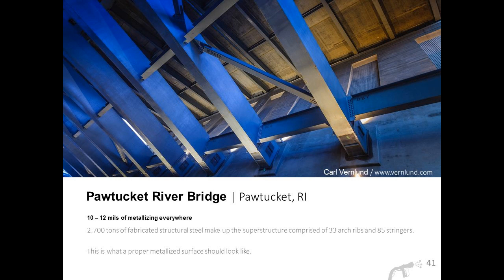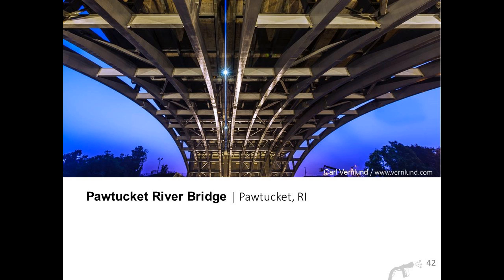So metallizing was used and was applied at a volume of about 10 to 12 mils and, like I said, seal coated and erected. There was no touch up in the field. The job went fairly smooth. So that gives you an idea what the underside of the bridge looks like, and there's a walkway underneath there.